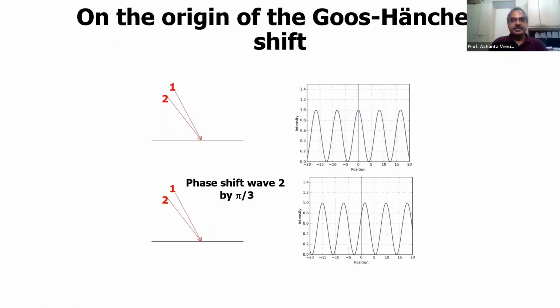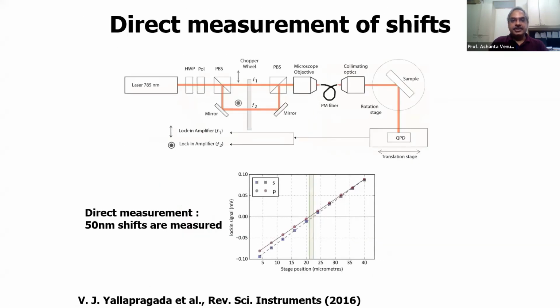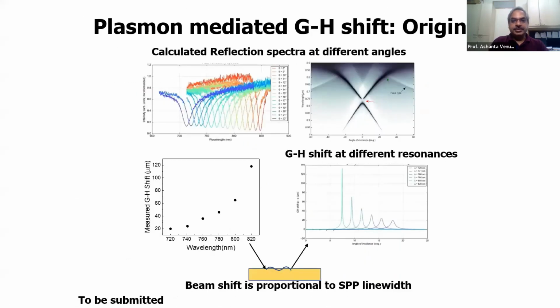There is another way to measure plasmon lifetime. I'll skip this. It's basically the Goos-Hänchen shift. In the case of plasmons, when you excite plasmons, they propagate along the interface and then couple to the far field. So if you look at the centroid of the incident field and the centroid of the reflected beam, you see that they are shifted in space.